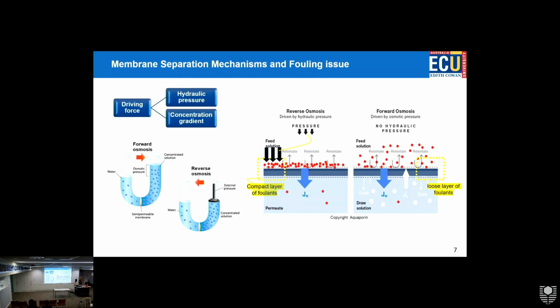And with reverse osmosis, because we apply pressure, the contaminants can accumulate on the surface. So we have a phenomenon that we call fouling. Fouling is the accumulation of contaminants on the surface or within the surface pores of membranes, which significantly affects the permeability. So it reduces the water production, and it reduces the lifetime of the membrane, because they accumulate and reduce efficiency. We have to clean the membrane. Lots of the time we use chemical cleaning processes, or even very harsh mechanical cleaning processes that damage the membranes. And this is actually the main reason why these membranes are ineffective in wastewater treatment plants: they have a 5-year lifetime, for example, based on the books, but in reality they are out after 3 years, or they have lots of defects that contaminants can pass through.